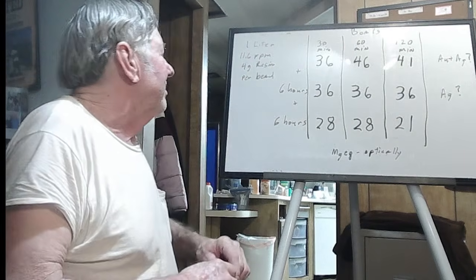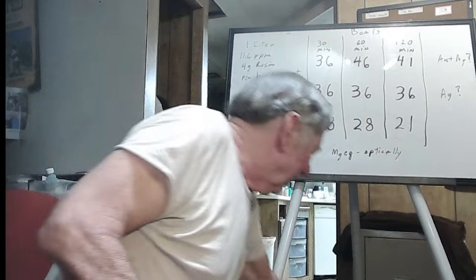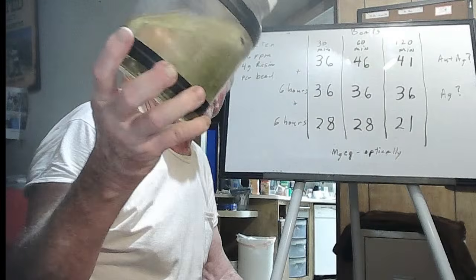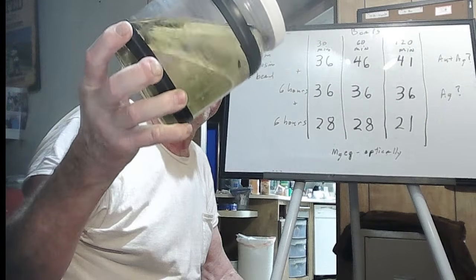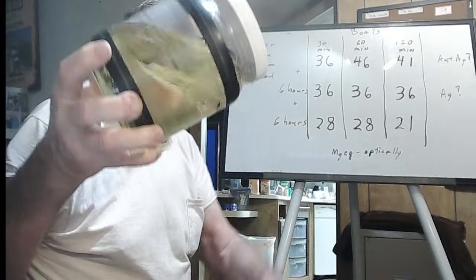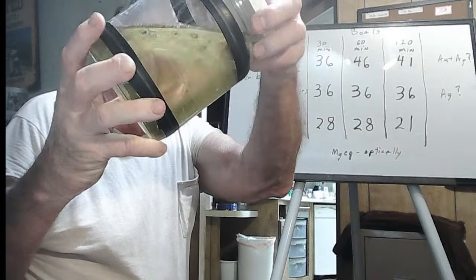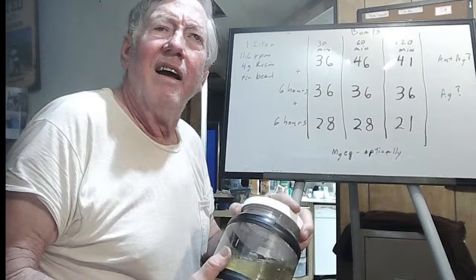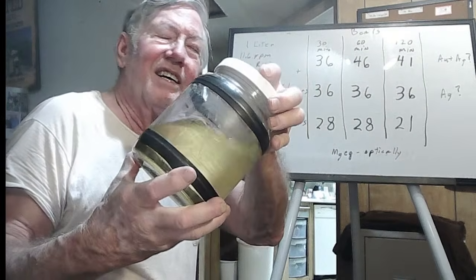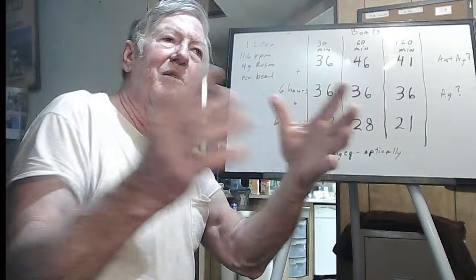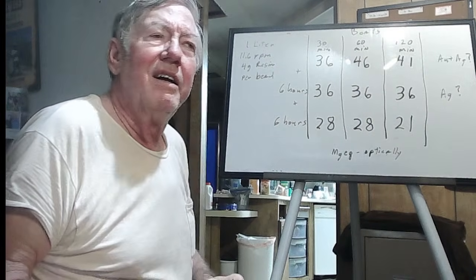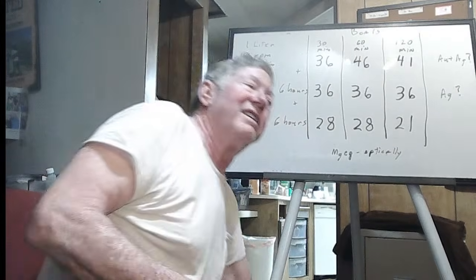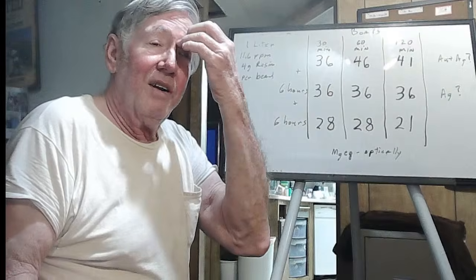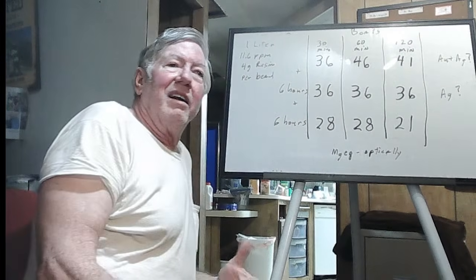Anyhow, one of the advantages, if in resin and pulp, let's say this was your mud, you got 1 part solid, 3 parts of Eco Gold X solution. This right here rolls. If this was a cement mixture, it would roll this way. If you put resin directly in there, it will absorb gold out of it, but it's going to do it very evenly. It's all going to absorb gold at the same speed. If you put it in solution like this, or if you just had what they call a fluidized bed column, where the resin mixes around, it'll also load very evenly.